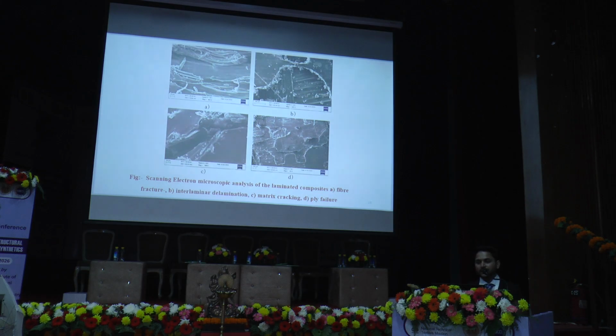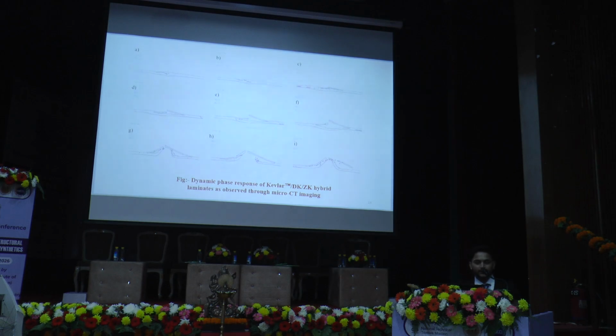Here you can see A is fiber fracture and B is interlaminar delamination. You can clearly see that the delamination occurs when the impact occurs and the fiber matrix interface is somehow deflected. Matrix cracking is also visible at C, and ply failure you can see here. This is the microCT imaging, which clearly shows how it behaves under this impact loading and how much bulge zone it created. This microCT helps us identify how much bulge zone was created and how much it resists penetration to the human head skull.